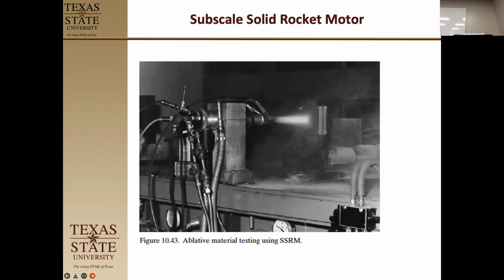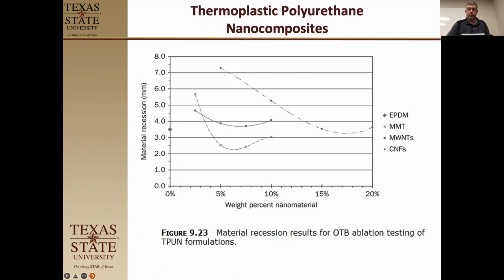And then you have your thing bolted or clamped down to where you burn. Usually you use a burn time of 50 seconds, if that's a typical rocket motor burn time. And then you analyze the surface. So this is a different setup than what they used. They used an oxyacetylene torch. This is actually set up to actually do ablative materials testing.